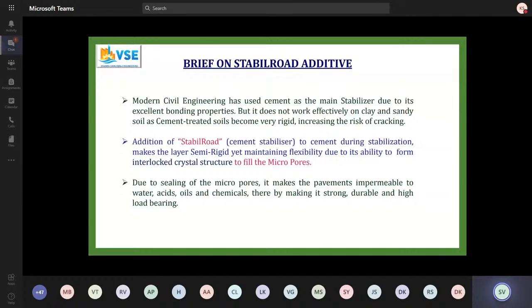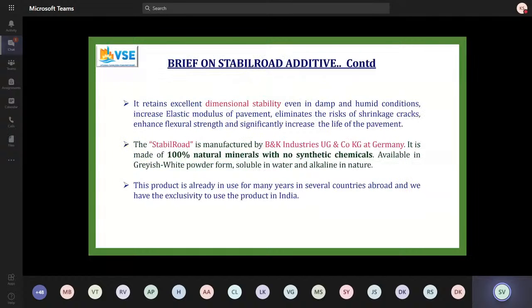Stable Road is a cement additive which makes the layer semi-rigid yet maintains flexibility due to its ability to form an interlocked crystal structure to fill whatever pores are there in between. Due to the sealing of the micropores, it makes the pavement impermeable to water, acids, and chemicals, thereby making it very strong, durable, and high load bearing. It retains excellent dimensional stability even in damp and humid conditions, increases the elastic modulus of the pavement, eliminates the risks of shrinkage cracks, thereby enhancing flexural strength and significantly increasing the life of the pavement.